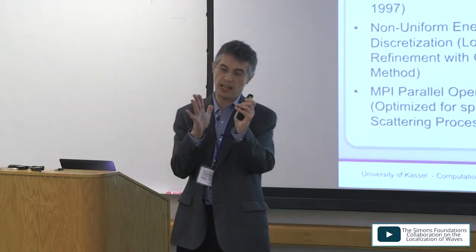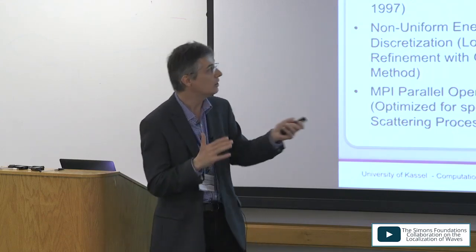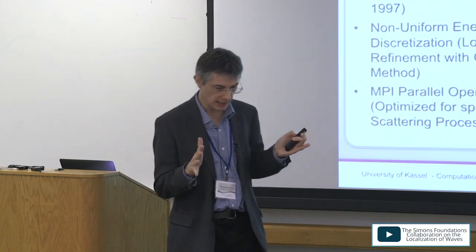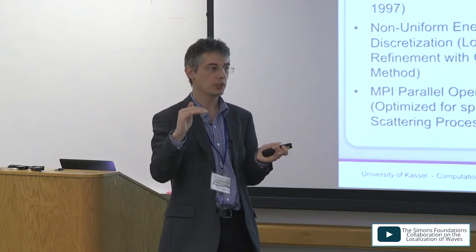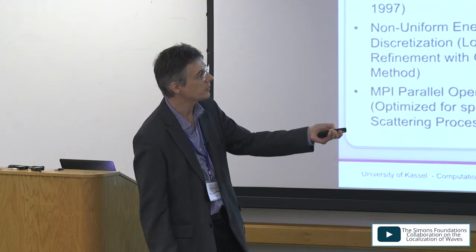And unfortunately, in the nitrides, due to the polarization charges and the Stark shifts, we need to iterate the nonlinear Poisson equation. For example, the people who are doing lasers are always looking at flat band potential or constant electric field. They will not do this loop of the nonlinear Poisson equation.